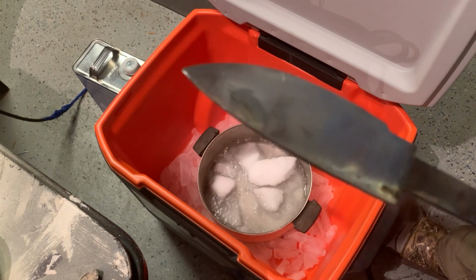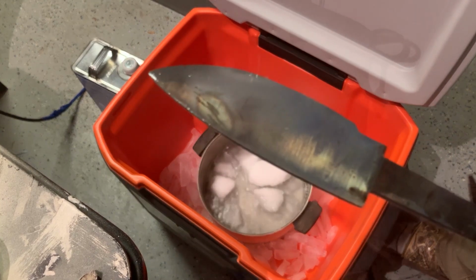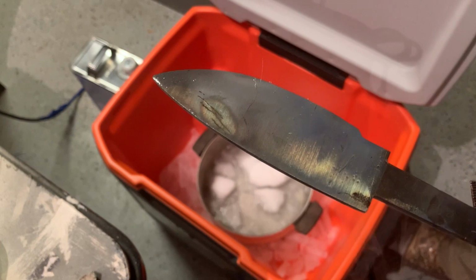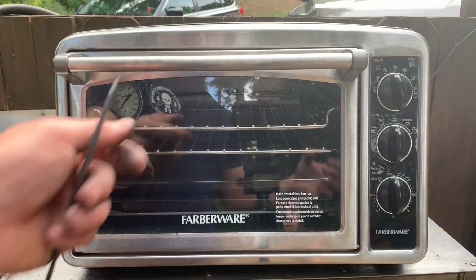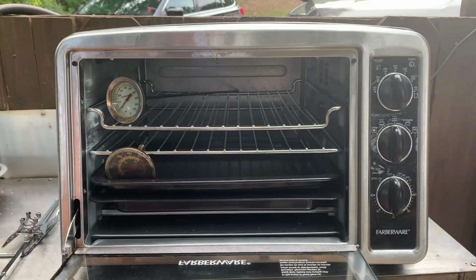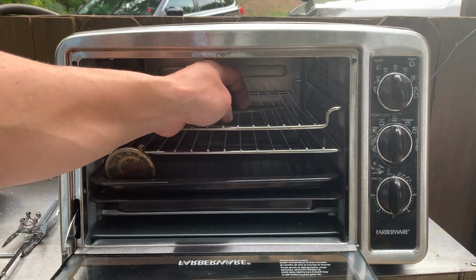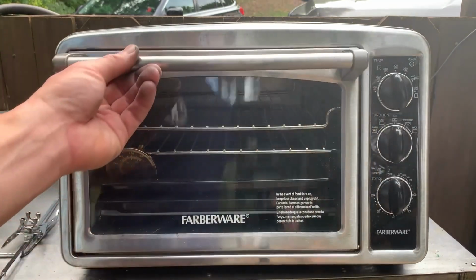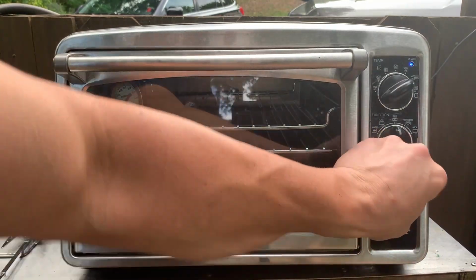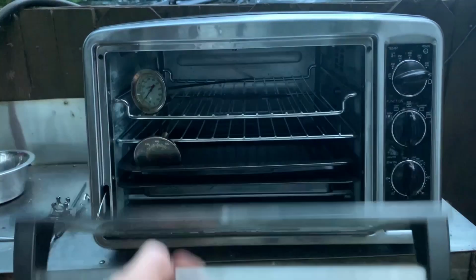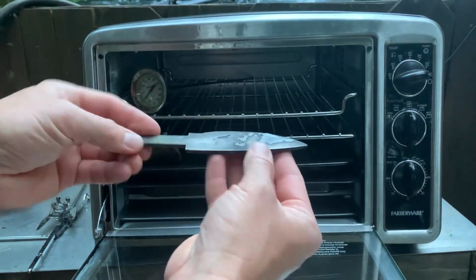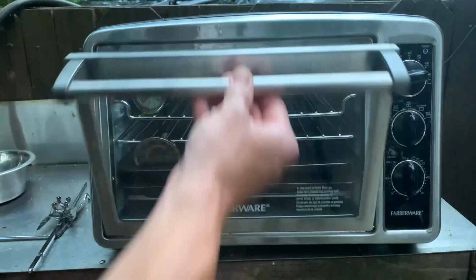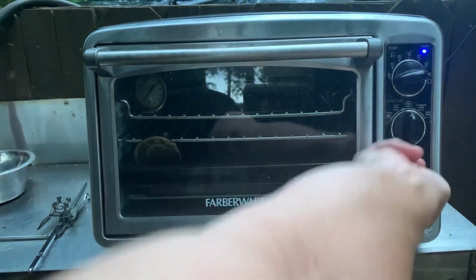I've seen people do this step for an hour, and I've seen them go all night. I went with all night, as there's no such thing as going too long. Next up is the easy step of tempering. For this, I simply bake the knife at 400 degrees Fahrenheit for 2 hours, allow to cool down slowly, and repeat. This keeps the knife from being too brittle while still retaining the good hardness qualities achieved by the previous steps.